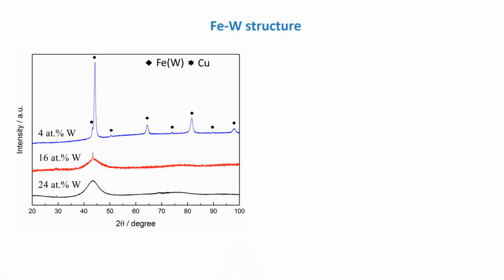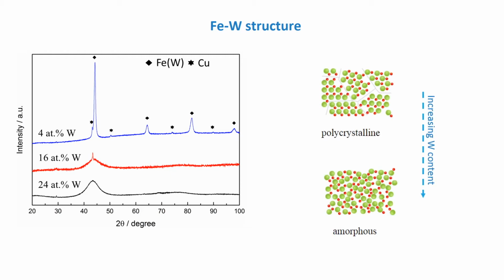I don't work directly with the deposition of the iron tungsten coatings. This is done by my colleague Aliona Nikolenko at Vilnius University. I study the structure and the properties of the material. So let's take a closer look. As shown by XRD analysis, the crystallographic structure of the as-deposited iron tungsten coatings changes with increasing tungsten content, passing from a nanocrystalline structure, which is found for the 4 atomic percent tungsten sample, to a homogeneous amorphous nature for the 24 atomic percent tungsten sample.